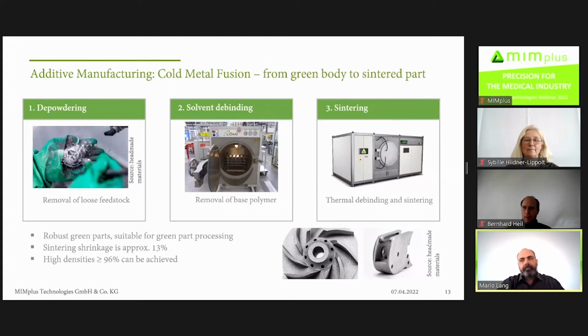At the end, I think at every process we can offer to you, you have a high density metal part with a closed porosity. The sinter shrinkage in this process is around about 13%, and you have quite robust green parts, so you can do some green part processing with them, like drilling or other processes, maybe some processes to make a better shape, to not have the big surfaces between the layer and so on.